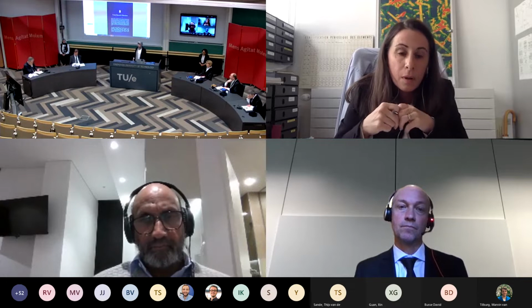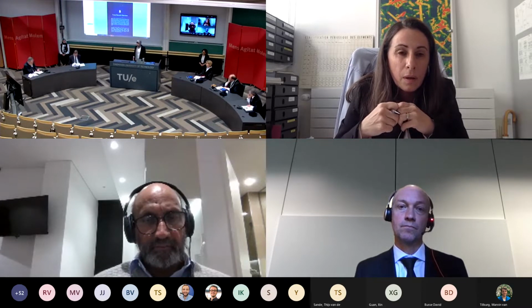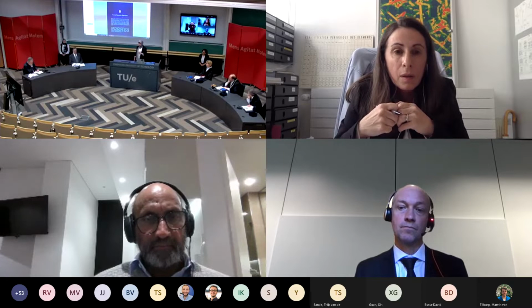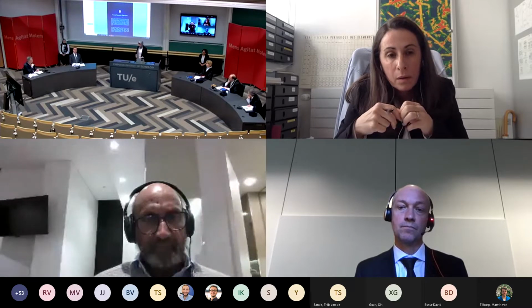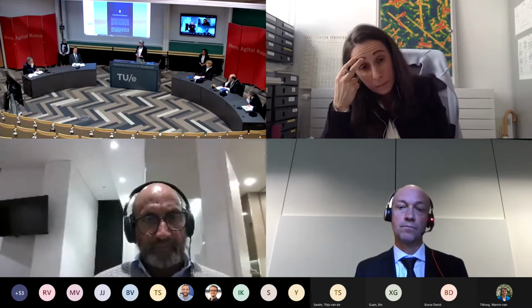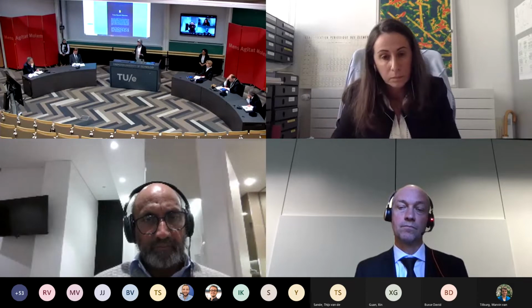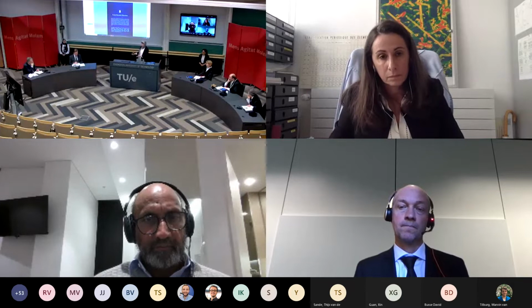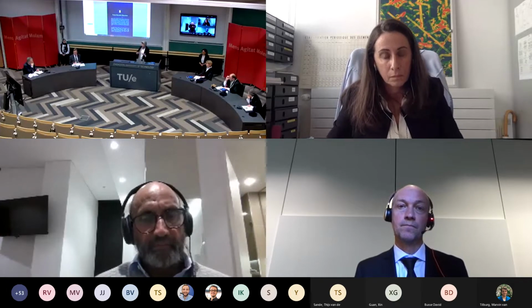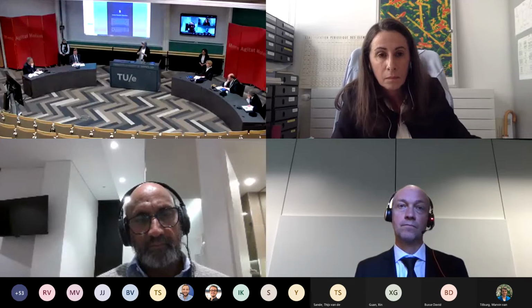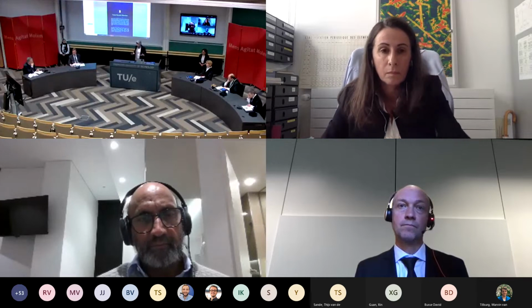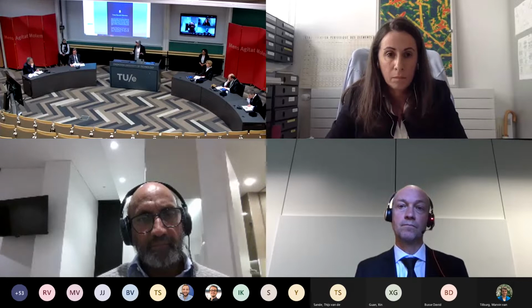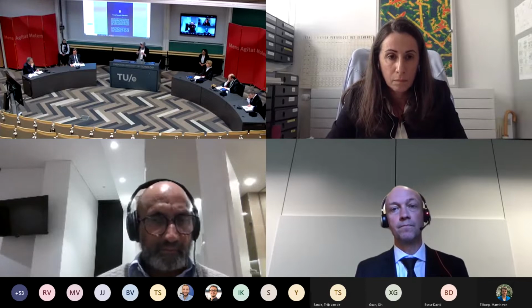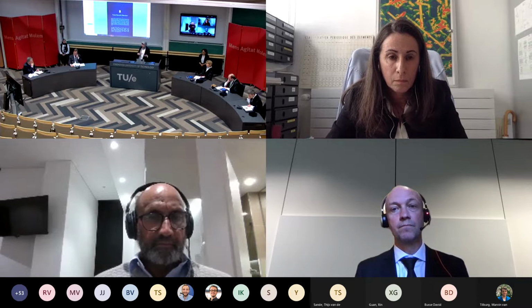Thank you so much for the questions. I'll start with the first question, about whether I have an idea about the potassium contamination on the surface of the gallium arsenide. To be honest, we didn't really investigate that in detail, but I'm pretty sure there is a correlation with the chemical etching step, which we know is quite dirty, because chemical treatments introduce some impurities or might cause roughness, in case there is nanoscale etching or roughening on the gallium arsenide. But knowing for sure if we have potassium or CN compounds, we have no knowledge about it, so we should further investigate it.